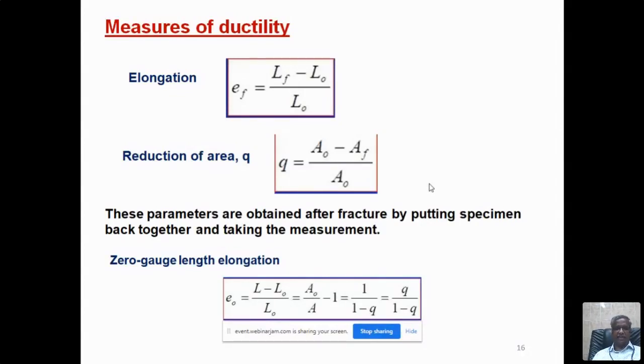And reduction in area is also a ductility parameter. You measure the diameter of the specimen initially and calculate the area of the specimen. After fracture, at the fracture point, measure the diameter again using a digital vernier caliper. If it is a sheet or plate specimen, you measure the thickness and the width and calculate the area. The initial area minus final area divided by initial area will give the reduction in cross-sectional area. So these two parameters will explain what ductility is.